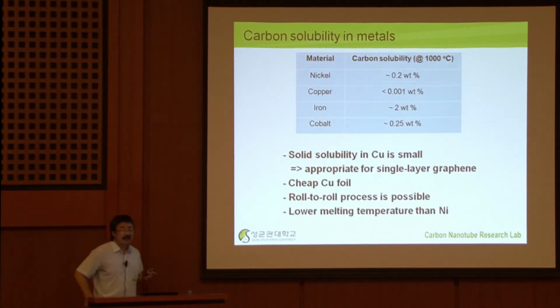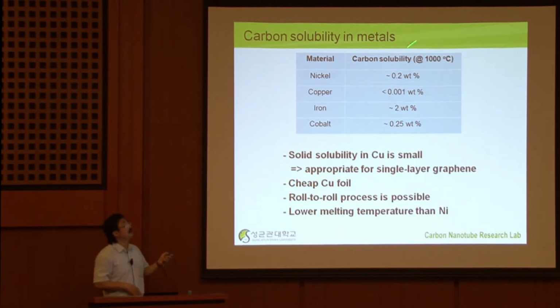It's because of this carbon solubility in metals. If you look at, for instance, nickel, nickel has quite high carbon solubility. So what happens during this large area CVD process, carbon first melts into this nickel layer, and then during the cooling, this carbon out-diffuses again because of the limited solubility, and then forms this graphene layer. But because of this high solubility, it's difficult to control the number of layers.